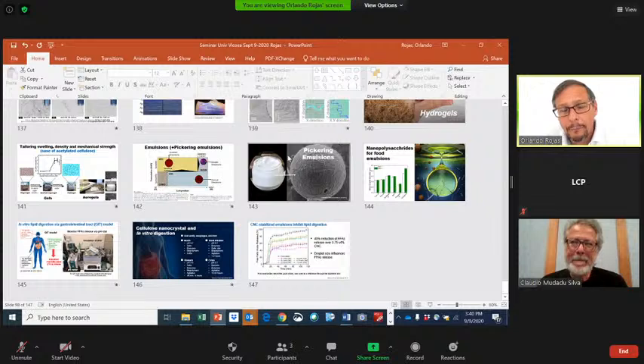Not that I know, but I do know that there are applications for CNCs in making banknotes for anti-counterfeiting purposes. So the use of iridescent patterns with cellulose nanocrystals has been tested. Also, the use of quantum dots together with nanocellulose, I believe, has also been used for banknotes. And there are developments in those areas. Not so much about the material itself, but as additives for, for instance, anti-counterfeiting and that type of application. But besides those, I'm not aware. And maybe it's difficult to know, right? Because usually those formulations are very well kept. But I can say that there are some, and there are some publications related to the topic.